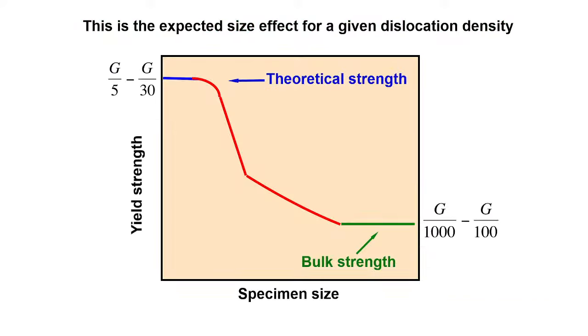So just to put this in a cartoon format, if I plotted yield strength versus the specimen size, at very low specimen sizes, you would get strengths that are close to the ideal, which is G over 5 to G over 30, which is the theoretical strength. And at very large pillar sizes, you get bulk strengths, which are G over 1000 to G over 100. And then there'll be some transition between the two, which we don't quite know, but let's imagine that it looks like this.